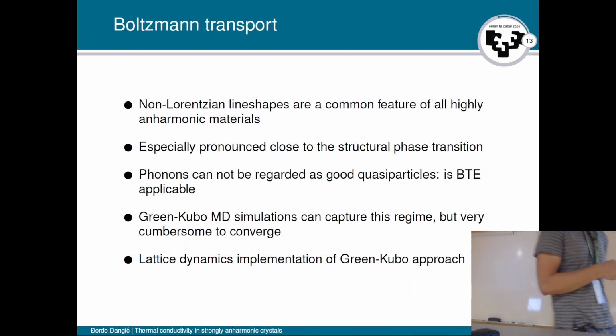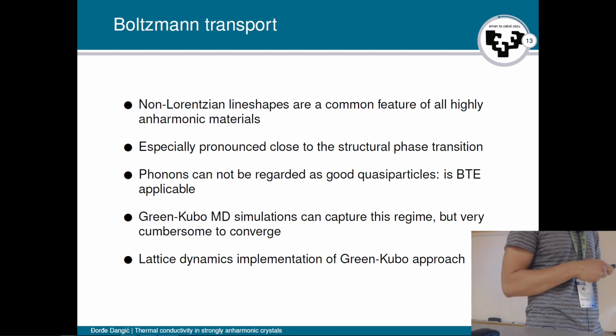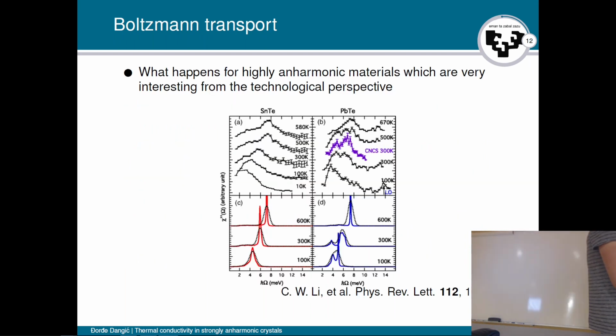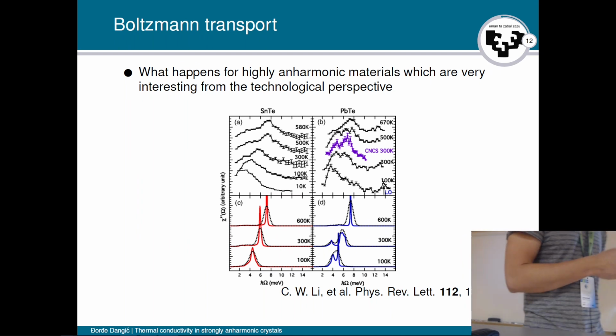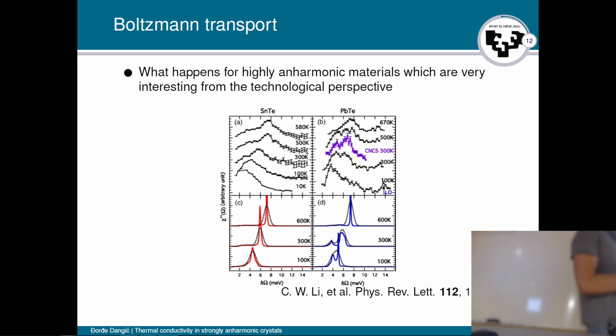Now, it's not just lead telluride that has these features. It is a pretty common feature of all highly anharmonic materials to have these non-Lorentzian line shapes. Additionally, they are especially pronounced close to the structural phase transition. And indeed, lead telluride is known as an incipient ferroelectric. So at very low temperatures, there is a bit of a debate whether lead telluride actually belongs to the space group that people usually assign it to. As you can see, at low temperatures it has this double feature, but as you increase the temperature, it becomes more cubic, and this anharmonic feature disappears.